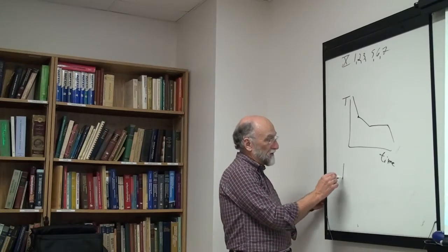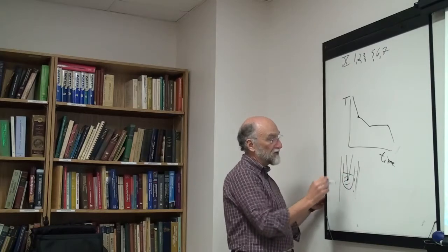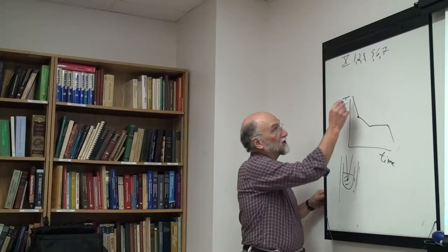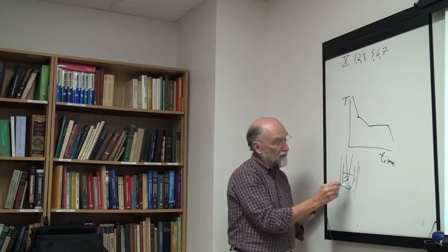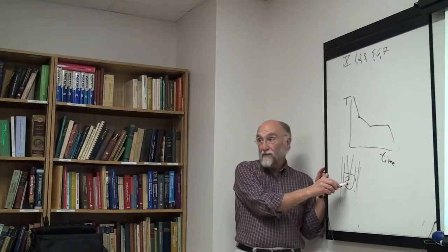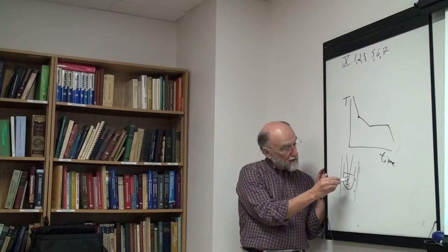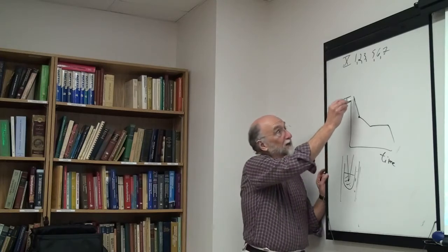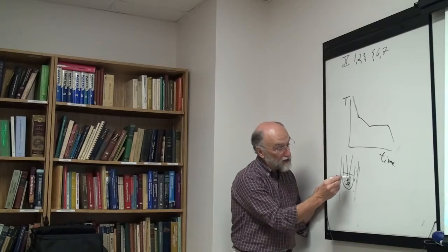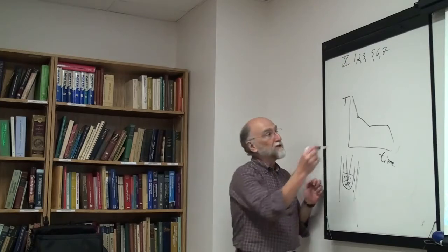The reason being, now if you take this is your furnace here, this is your sample, you put a thermocouple in the sample and you cool it down slowly with some stirring. So the temperature of the furnace is going down slowly. When the thing starts to solidify, it gives off heat, and that slows down the cooling within the sample. The furnace is cooling outside, you're slowly ramping down your furnace. But when the solid starts to precipitate, heat is being generated within the sample, and that slows down the cooling within the sample. Okay, so you get a change of slope.